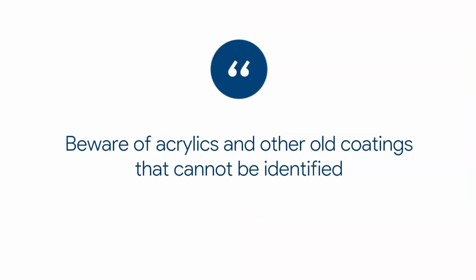And another point to make is, a lot of times you might have other types of floor coatings like acrylics or an old coating that is so old you can't even tell if it's epoxy, polyurethane, acrylic, or something else. In general, when you work with these surfaces, you always want to be on the safe side. Do a good sanding first, see if the coating can be removed. If you can remove it, just remove it instead. Prime it, make sure that there's no reaction in the primer, and then apply epoxy on top.